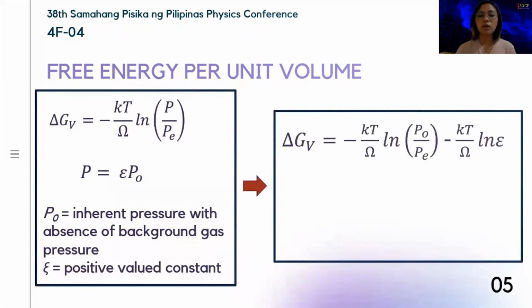Combining this equation, we will get a semi-quantitative behavior about the dependence of delta G sub V to the varying background gas pressure as seen in the equation. For constant substrate temperature experiment, the change in the free energy per unit volume decreases as the coefficient of epsilon increases. Since delta G dictates the growth mechanism of the film, it can predict the resulting properties of the film.